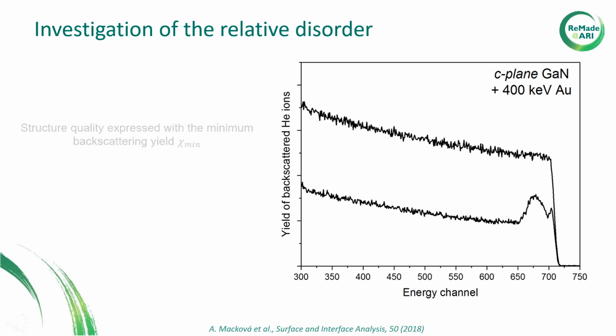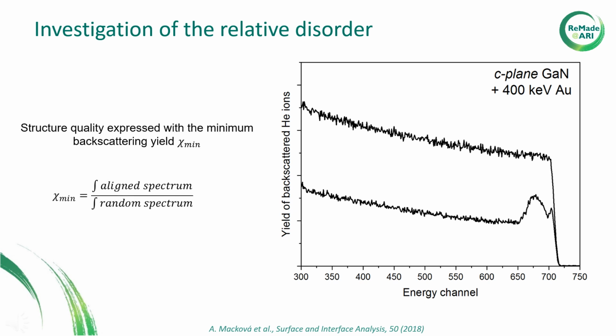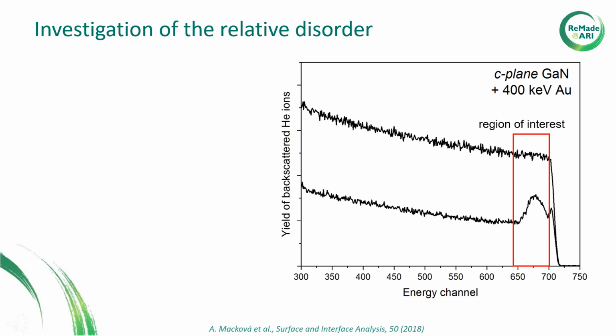The first idea about the structure quality is given by determination of the minimum normalized yield, which is given as the ratio between the integral yield in aligned and random spectrum. Usually, we are focused on a particular region of interest defined by chosen energies, and the integration is done only in the corresponding energy range. Knowing the minimum normalized yield of the disordered crystal and the perfect crystal, we can calculate the relative number of dislocated atoms in the disordered crystal.